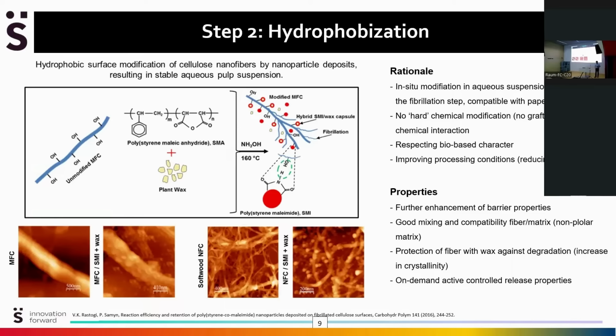So in the second step, we already talked about how cellulose is very hydrophilic, and often a hydrophobic modification of the nanocellulose is applied. It's often done by hard chemistry, by grafting techniques, for example. Here in this technique, we have deposited hydrophobic nanoparticles, which contain about 70% carnauba wax, that are physically attached to the nanocellulose and turn it hydrophobic.